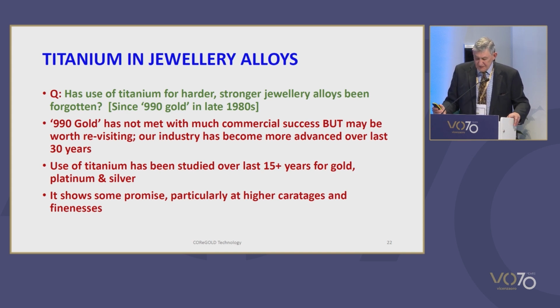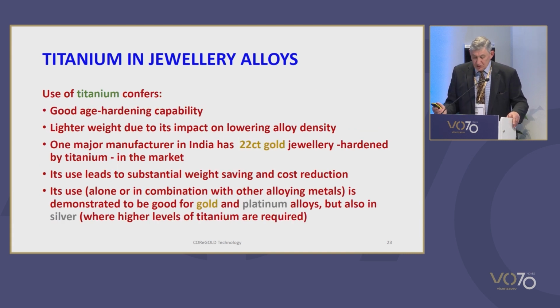As detailed in this paper, the use of titanium as an alloying metal has been studied further over the last 15 years for gold, platinum and silver, and shows some promise, particularly at the higher caratages and finenesses. Its use confers good age hardening capability, and it has benefits in terms of lighter weight jewellery as it lowers alloy density significantly. As noted, one jewellery manufacturer in India has recently funded development of a titanium-containing 22-carat yellow gold alloy that is now in commercial production for jewellery application. Its use can lead to substantial weight saving with a concomitant lowering of cost.